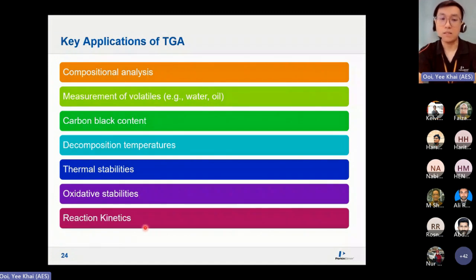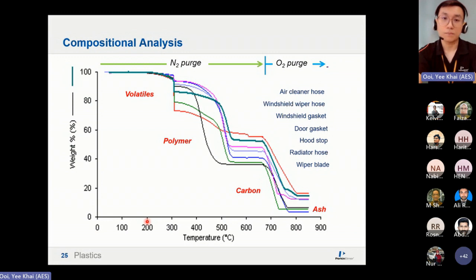Then reaction kinetics. For TGA kinetics, we are using the curves method, what we call a minimum 3 curves method, run at different heating rates. So if you want to do kinetics to simulate the shelf life of the materials, okay, then you can use TGA to do that as well, to do the predictions. So the typical curve, or typical thermogram, that we are going to get is something like this.